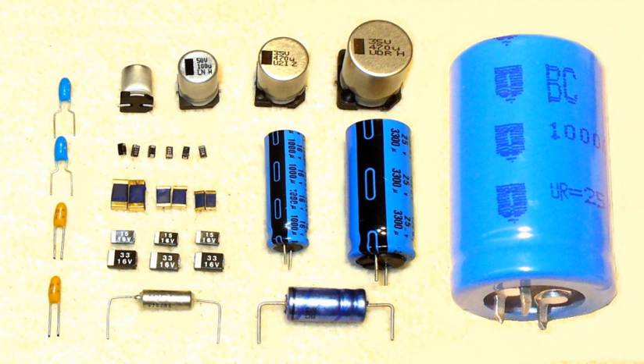It is good to know that for tantalum capacitors the failure rate is often specified in essence at 85 degrees Celsius and rated voltage UR as reference conditions and expressed as percent failed components per 1000 hours, n%/1000 h. That is, n number of failed components per 10^5 hours, or in FIT the 10,000-fold value per 10^9 hours. Tantalum capacitors are now very reliable components. Continuous improvement in tantalum powder and capacitor technologies have resulted in a significant reduction in the amount of impurities which formerly caused most field crystallization failures.